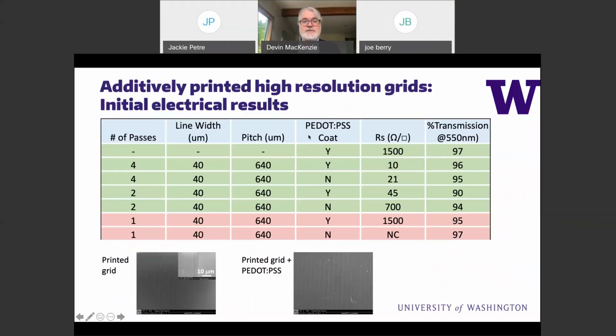In this example you can see we have some limitations, but the transparency is 96%, and that's a combination of printed grid plus, in this case, PEDOT:PSS, but heavily doped PEDOT. This is like OLED grade PEDOT. I can't remember the resistivity, but this is the HTL or hole injection layer type OLED material, which is relatively low conductivity, high resistivity. And with that, we get 10 ohms per square on that. So pretty promising stuff.